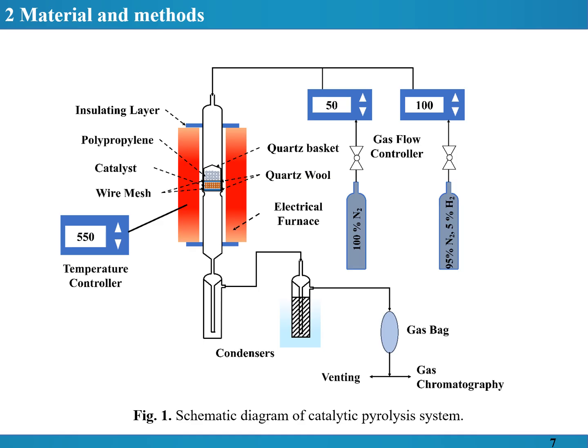Here's the experiment. First, place 1 gram of PP particles into the quartz basket, and place the quartz basket into the quartz reactor. Then put the quartz reactor under nitrogen flow and heat the electric furnace to 550 degrees Celsius. Then insert the quartz reactor into the electric furnace, connect the quartz reactor to condensers, attach a gas bag to the outlet of the condensers, and conclude the experiment after 1 hour.